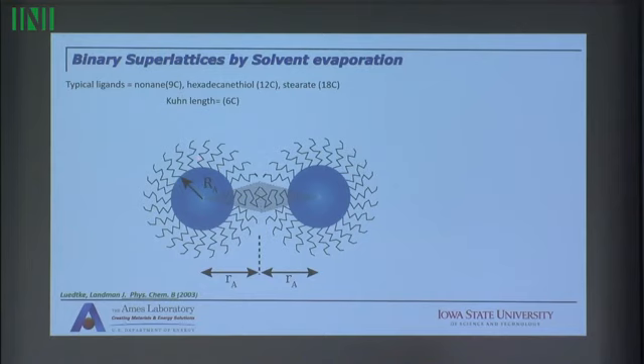One thing I should point out is that this is actually a short surfactant. So this is typically, for example, nonane or hexadecanethiol or stearate. What that means is that here we have 9, 12, 18 carbons. The Kuhn length is about 6 carbons. So here you don't have a polymer. This is not a polymer system, okay? So all the descriptions that you know in terms of polymers, in terms of brushes and things like that, do not apply here. You cannot use those because they are not valid. So you have to come up with some other description.